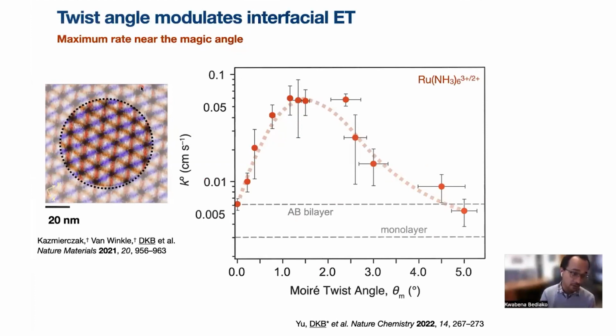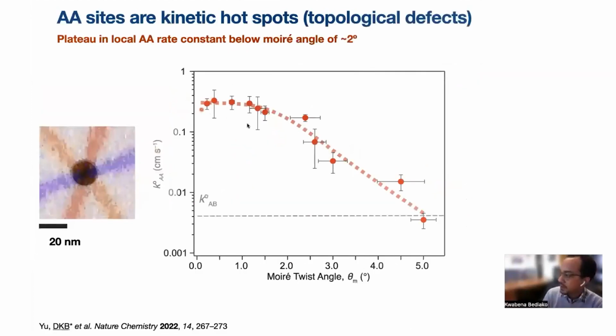Since from our 4D STEM measurements we also know the area fraction of AA and AB and so on, we can take this ensemble measurement and pull out the rate constants associated with the AA sites alone. And what we find is that they follow this trend where their activity, their rate constant, increases as you decrease the total Moiré twist angle, and then below about 1.5 or 2 degrees, it reaches a plateau.